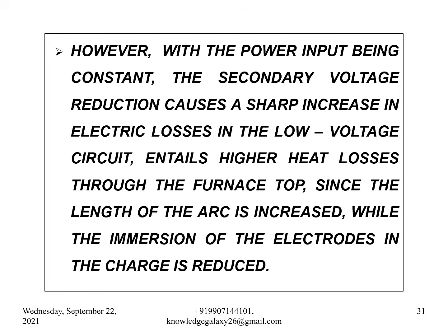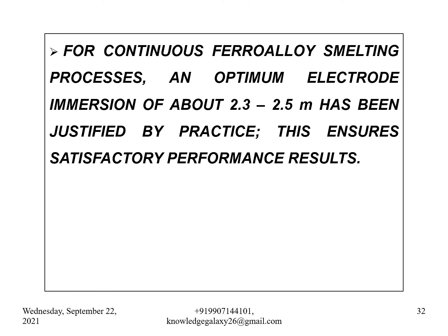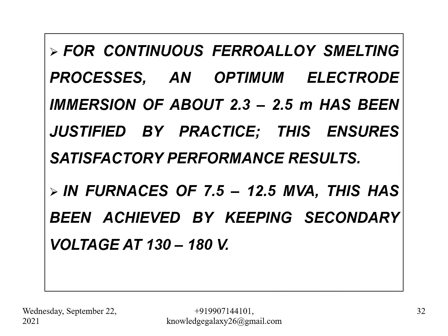However, with the power input being constant, the secondary voltage reduction causes a sharp increase in electric losses in the low voltage circuit, entails higher heat losses through the furnace top since the length of the arc is increased while the immersion of the electrodes in the charge is reduced. For continuous ferroalloy smelting processes, an optimum electrode immersion of about 2.3 to 2.5 meters has been justified by practice. This ensures satisfactory performance results. In furnaces of 7.5 to 12.5 MVA, this has been achieved by keeping secondary voltage at 130 to 180 volts.